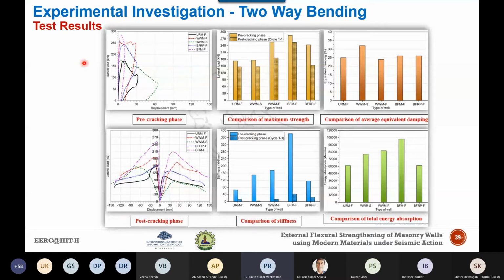Now if you see all these graphs, there is clear evidence of increasing pre-cracking strength and stiffness. See, here the unreinforced masonry strength is just around 170 kilonewtons. For wire mesh, the strength has increased. For fiber mesh, even for the FRP, the strength has increased. Not only the strength, similarly you can see also for the stiffness part. So there is a tremendous increase in the strength and stiffness, except for the wall with the flexible diaphragm condition. Here there is no strength increment.